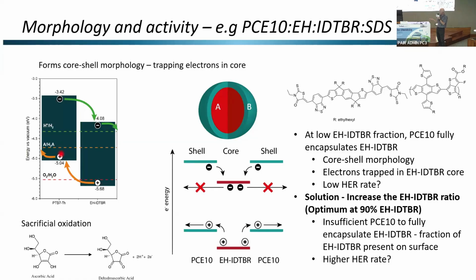However, when the hole is transferred to our donor, you now see that this is a thermodynamically unfavorable situation with regards to water oxidation. So what we do instead of water oxidation, we have to add at this point a sacrificial oxidation agent. And so we add ascorbic acid, and this is an oxidation process that has this potential here. So we know that our holes on our donor are still sufficiently active to drive this ascorbic acid oxidation. So it's oxidized to this diol, the ketone product here.